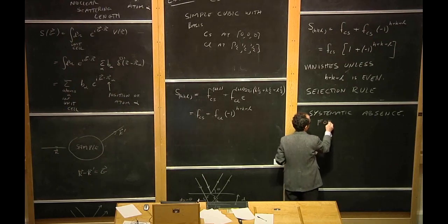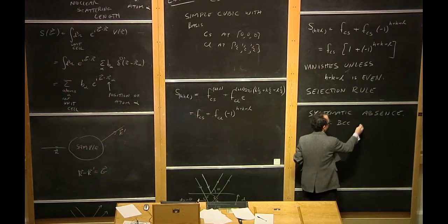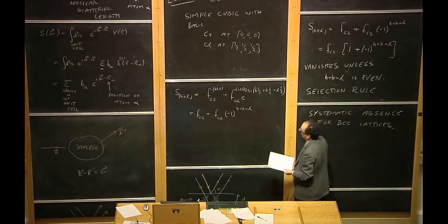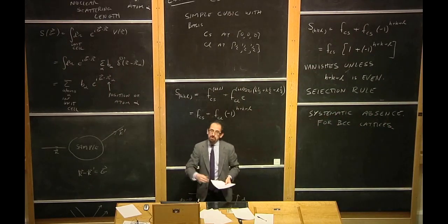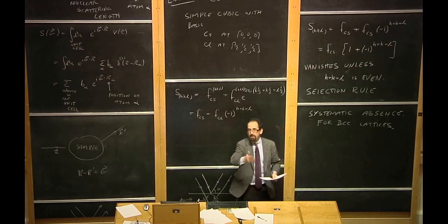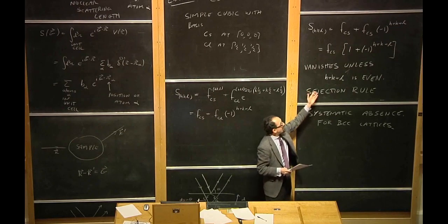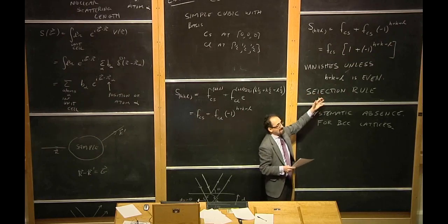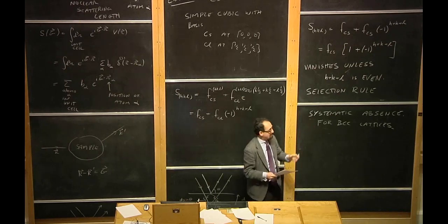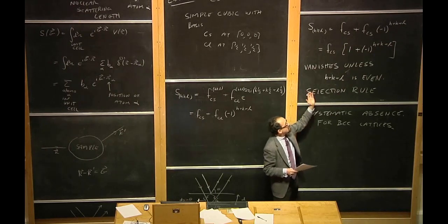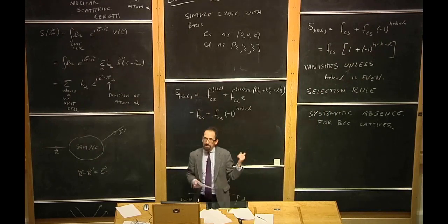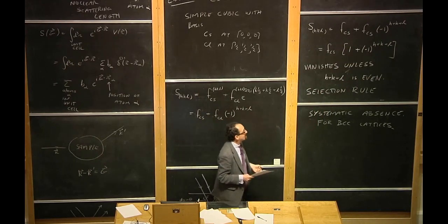These are the selection rules. Now, whenever you do a scattering experiment, if you discover that for all the Miller indices scattering by these wave vectors, h plus k plus l odd shows no scattering, but you do find scattering for h plus k plus l even, it's a very, very good bet that what you have is a BCC lattice.